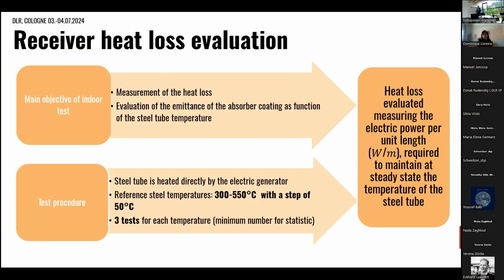The test procedure is to heat the steel tube directly by the electric generator. We have performed the test in the range of temperature between 300 degrees and 550 degrees, with a step of 50 degrees. And for each temperature, we have performed 3 tests. The heat losses are evaluated by measuring the electric power required to maintain the steel tube at steady state.